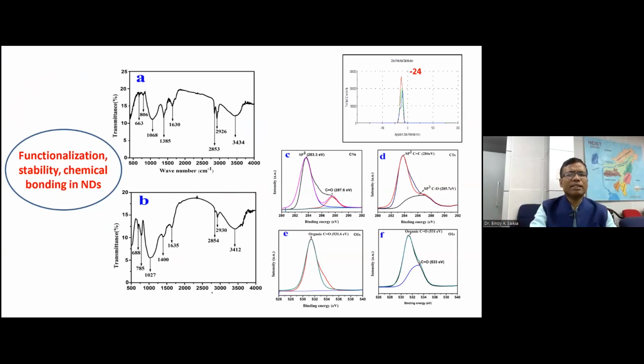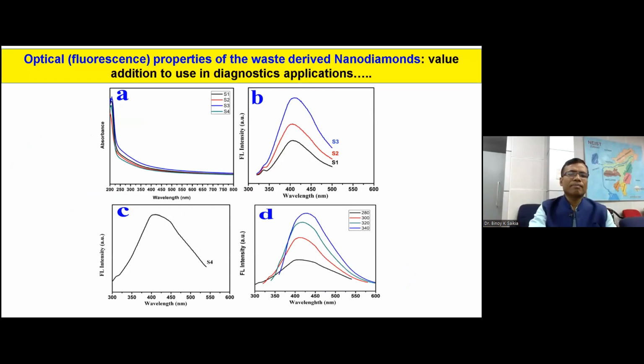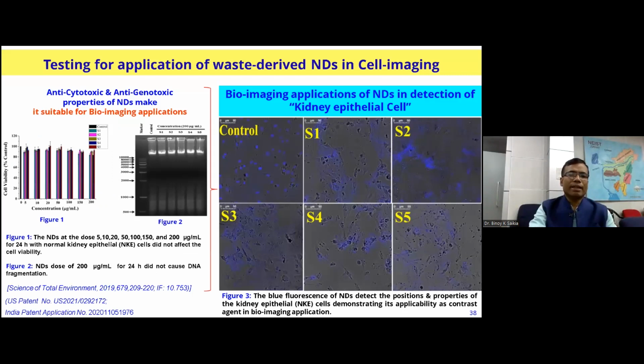And the functionalization and stability of diamond is very important. So we also tried to see the stability, and we found a zeta potential in the negative region, -24. So it establishes that the diamond particles made from this type of waste materials are very stable. So it can be applied for different applications. And for the optical properties, we found that it is in the blue region, with emission around 400 to 450 nanometers, but it is also excitation dependent, which is very necessary for diagnostic applications.